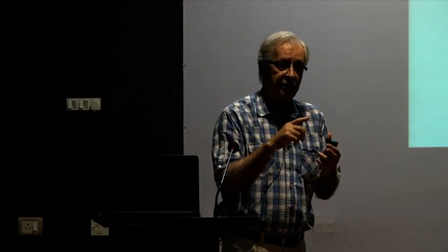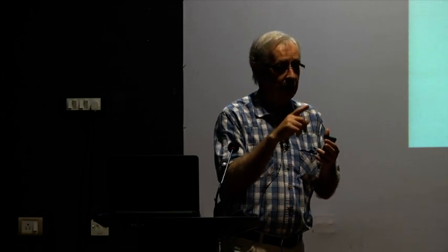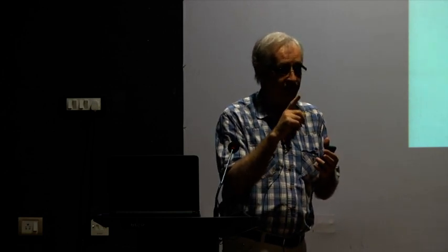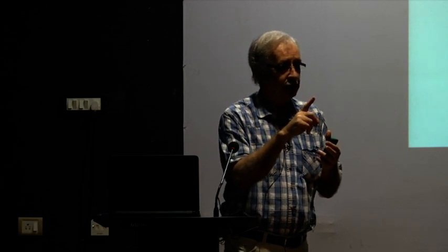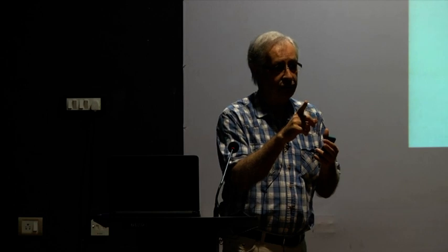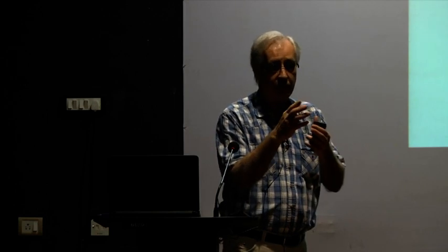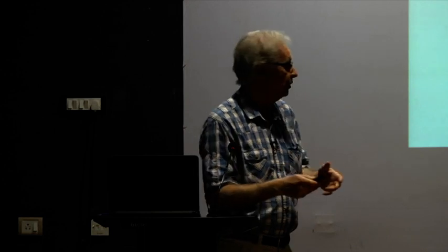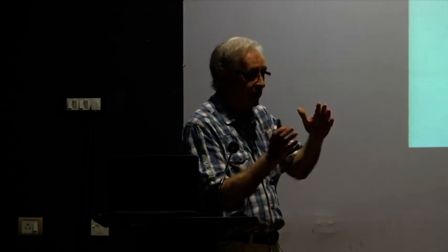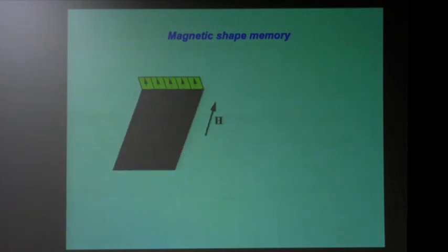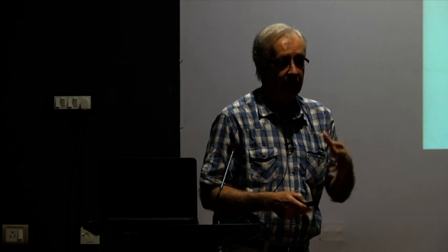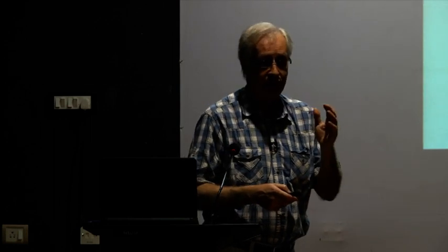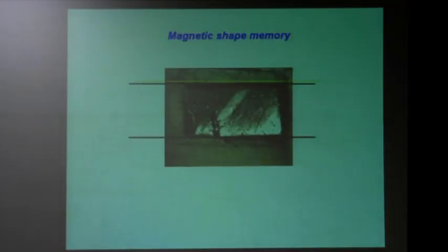The case here in nickel manganese gallium is that the magnetization is very strongly pinned to the lattice. So any rotation in the magnetization causes, along with it, a rotation of the crystal structure, almost the crystal itself. So you're rotating the whole parallelogram here, let's say, along with the moment itself. So there's a very, very high magnetocrystalline anisotropy associated with this. So in a real system, it looks like this. This is a real single crystal.